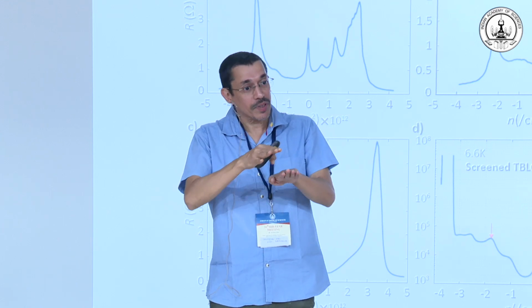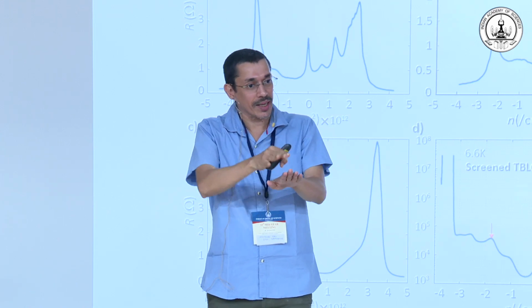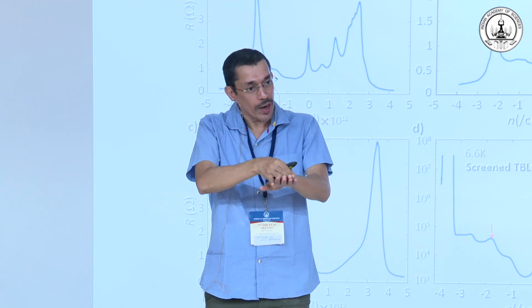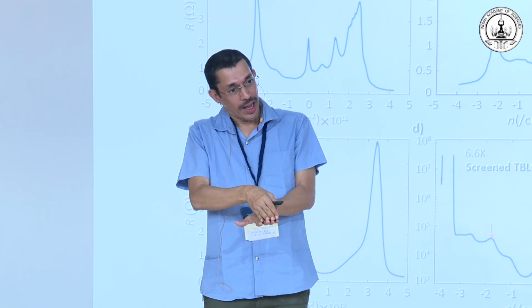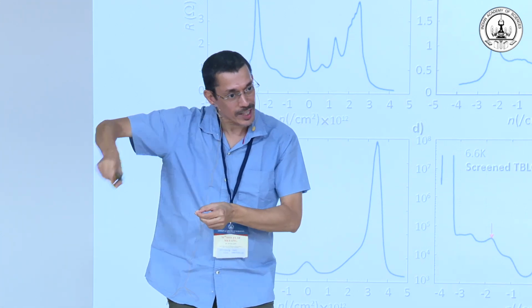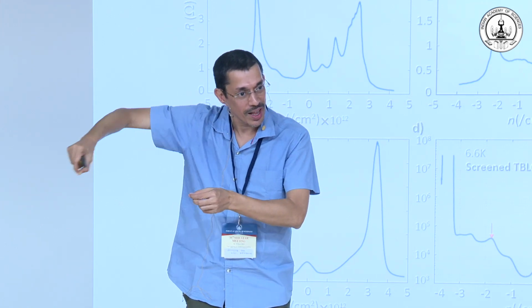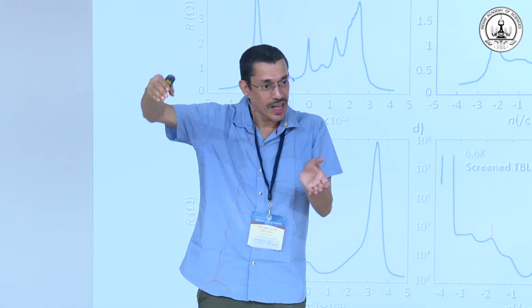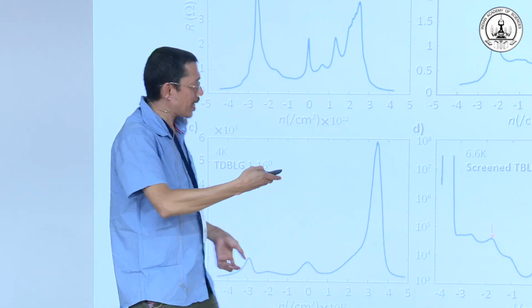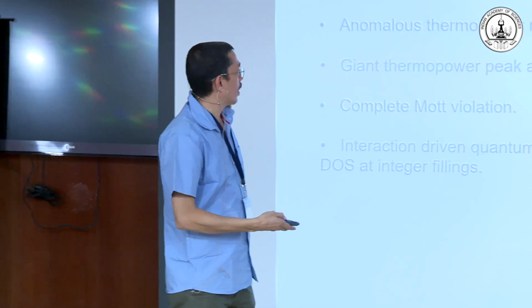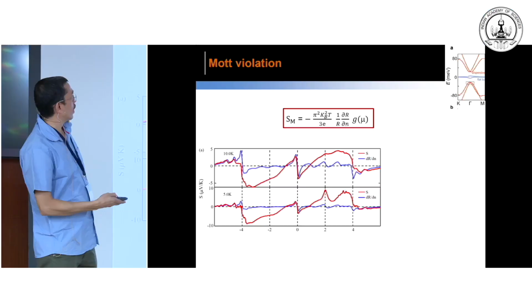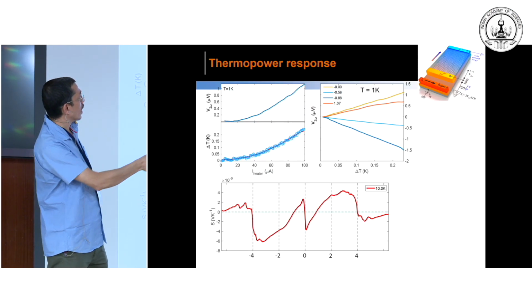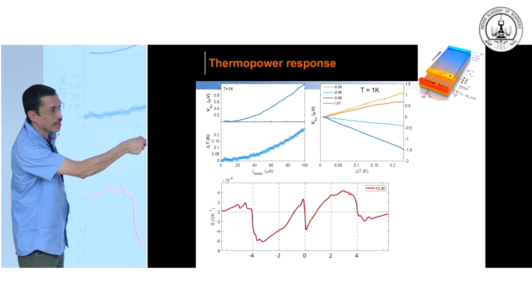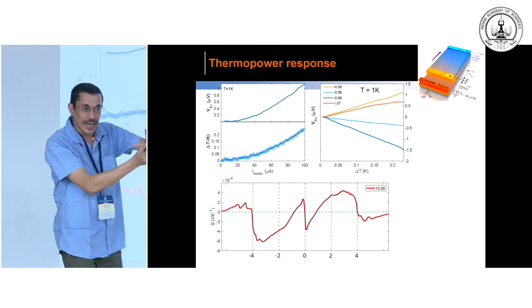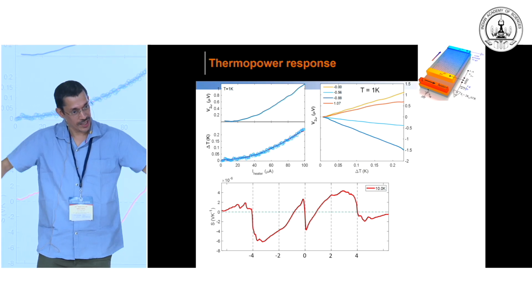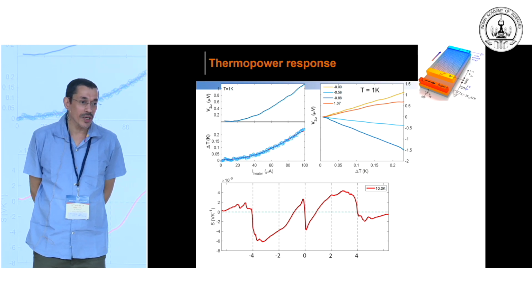But some device, let's say it's statistical, some device maybe doesn't relax, and once it becomes room temperature, they're stuck. Now, once you form the contact, contact has a 1D bond, one-dimensional bond. So now you cannot move it, right? Because the contact has been written. It's like a constraint from the end. So the entire thing is clamped? Yeah, you have some angle, but you have a contact now. Now you cannot rotate the relative angle because there is a support. The two rods are there, so you cannot.